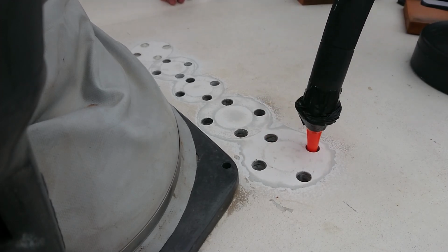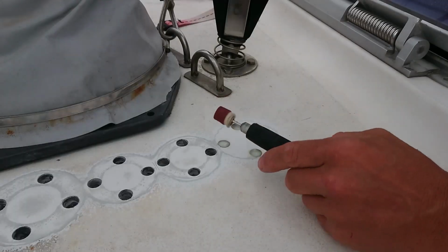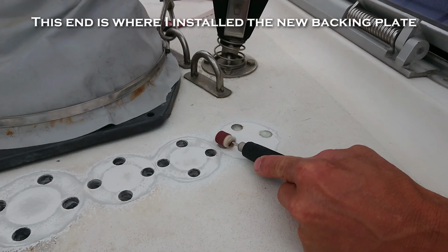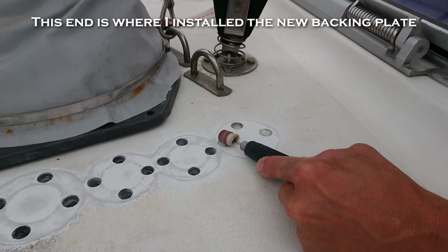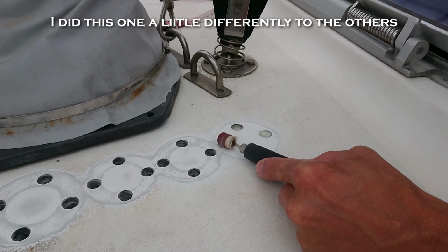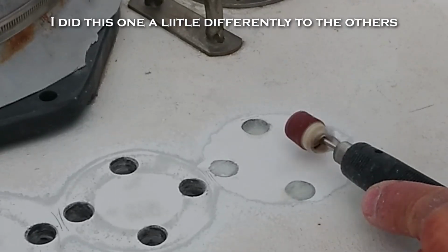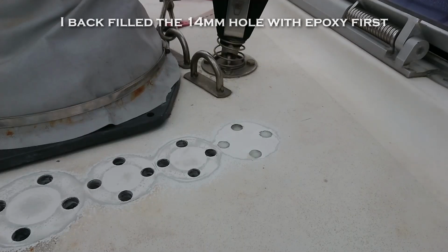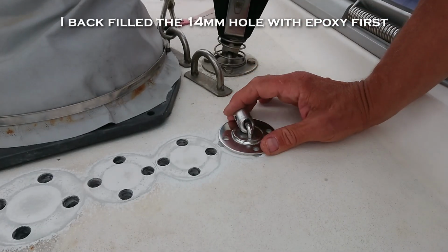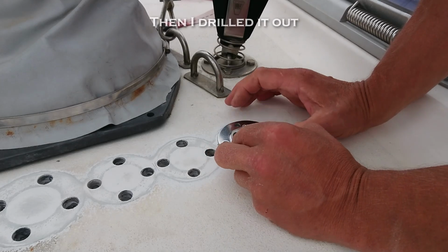Before I do that though, I'm going to fit that new deck block. I'm sanding the top of the cured epoxy nice and flat so I can mark it and the drill bit doesn't skip. You can probably see that one of the holes is a touch less than full, and this has probably happened due to an air bubble getting trapped in as I filled the hole in, and the epoxy's settled and sank as it's been curing.